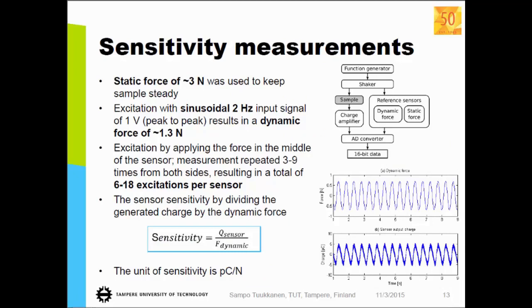First you apply about 3 Newton static force to keep the sample in place, and then above that you put the dynamic sinusoidal force. We have used 2 Hertz excitation, and finally you can use the charge amplifier. Here is the schematics of the system. So you have the sample, then you have a charge amplifier which gives the amount of charges when you have applied the mechanical force on the sample, and then you can calculate the sensitivity by dividing the charge with the dynamic force.